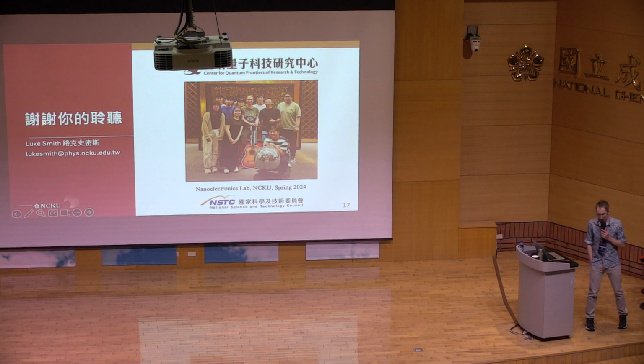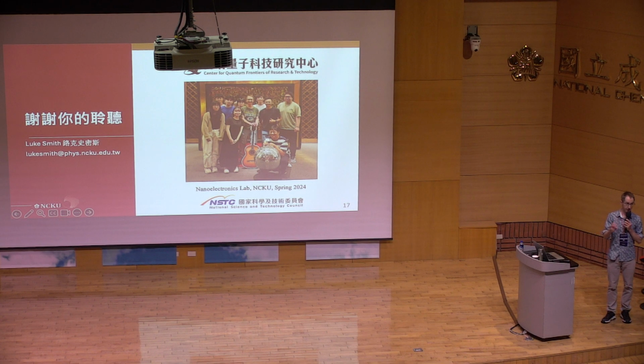Now, we use a very, very low power to do this oxygen plasma treatment very deliberately, so it's only 10 watts, the lowest power setting on the system, just to keep it as gentle as possible to prevent any damage. Okay. Any other questions?